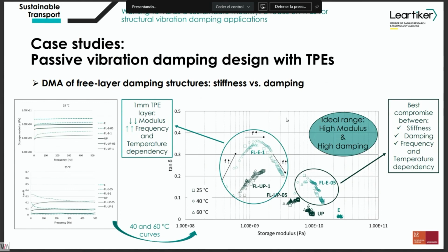What we did, as I said, was a temperature sweep test. As you can see on the left, we have also performed a room temperature frequency test. But what usually happens when performing different DMA tests, frequency and temperature, is that you get a lot of graphs, and it is not very easy to compare different materials and structures for the target that we have in mind. In our case, it is a component that needs very good damping at room temperature and high stiffness values, because we want to add TPE to improve the vibration damping, but not to reduce the stiffness or structural contribution that SMC gives to this kind of application.